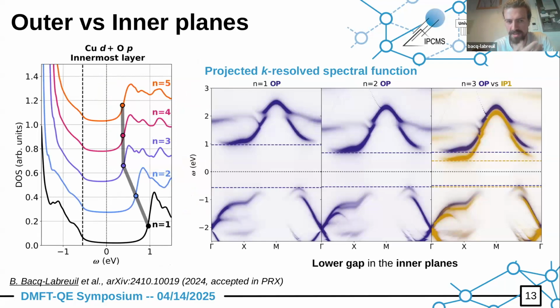Then we can ask, well, why is there this reduction of the charge transfer gap? So we can look at the spectral function resolved in momentum. This will be basically your spectral function measured in ARPES, say, if you would look below the Fermi level at 0. And you can see that here I plot for n equal 1 and n equal 2, there is only a purple spectrum, which corresponds to the spectrum of the outer plane, right? And you can see that there is basically just a reduction of the charge transfer gap in these outer planes. But as you go to the right, to the tri-layer compound, now we have both outer planes and inner planes. And you can see that the outer plane remains relatively constant with respect to the n=2 compound, but the inner plane has a smaller gap.